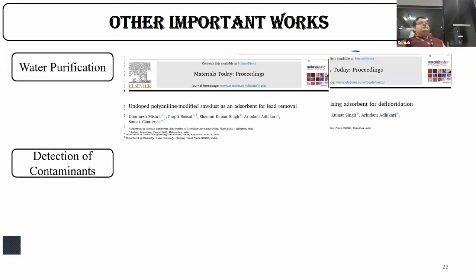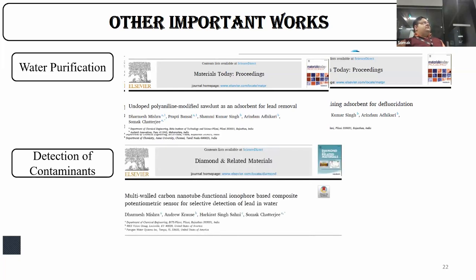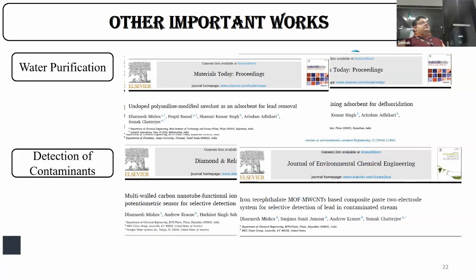Water purification is an integral part of an entire filtration setup, so apart from that, you also have to take into account the detection of contaminants. For detection, we used something known as a composite paste sensor. This was our first work, published in Diamond and Related Materials, where we used a functional ionophore to detect lead in water. Apart from that, we used a MOF, an iron terephthalate MOF, for selective detection of lead in a contaminated stream.